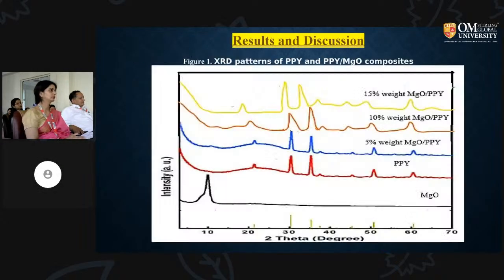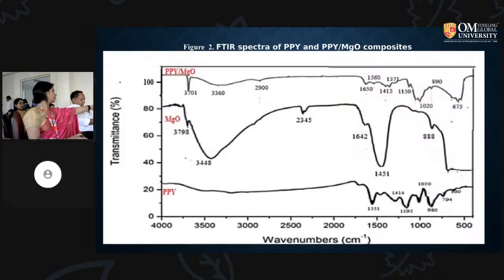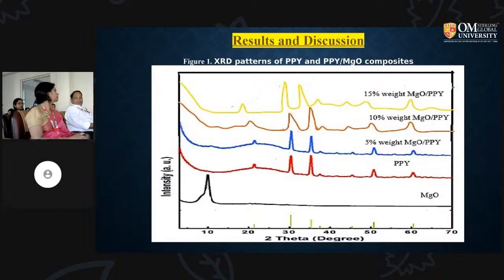Result and discussion. X-ray diffraction analysis. Polypyrrole and polypyrrole magnesium oxide composite XRD patterns are displayed in the first figure. Two identical peaks at 20.36 and 25.01 degrees are seen in the polypyrrole and polypyrrole magnesium oxide composite sample XRD patterns, while a shoulder appears at 16.10 degrees. The peak strength changes significantly when magnesium oxide nanoparticles are introduced to polypyrrole, demonstrating the strong interaction between magnesium oxide and polypyrrole. These peaks are caused by the quinoid and benzenoid rings in the perpendicular and parallel orientation. The processed samples show two peaks, indicating a quasi-crystal structure.